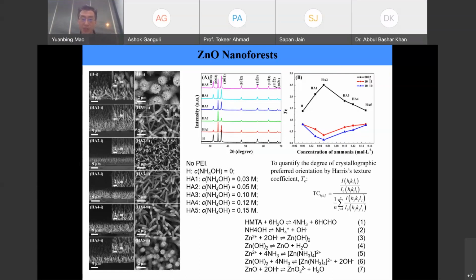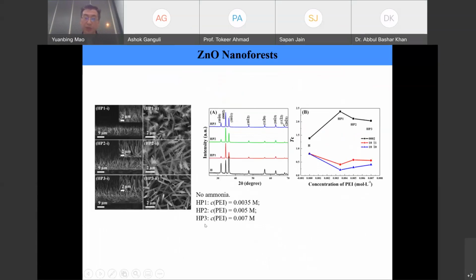Okay, so this part is basically where we didn't add PEI, right? But one thing we can notice is that under certain conditions it works best, so that's why we picked the condition in terms of the ammonia concentration. Before I go to that, I want to point out the other thing as well. In this part, we didn't add ammonia, so we changed the PEI concentration, and you will see that these branches are actually not very good. So PEI without ammonia doesn't work well if we want to grow branches, right?